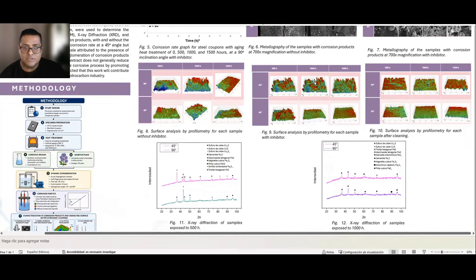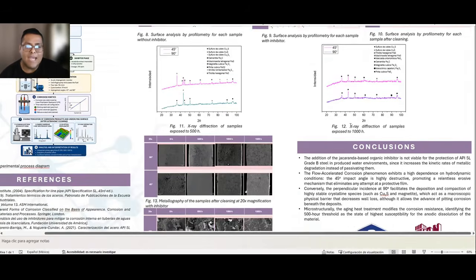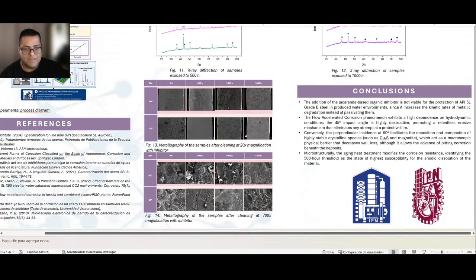And in conclusion, we have three main conclusions. First, the addition of this Jacaranda-based organic inhibitor is not valid for protecting this steel in produced water environments because it increased the kinetic rates of metallic degradation, inhibiting passivity. Second, the severity of flow-accelerated corrosion depends heavily on the hydrodynamics. The 45-degree impact is highly aggressive and it promotes constant erosion.